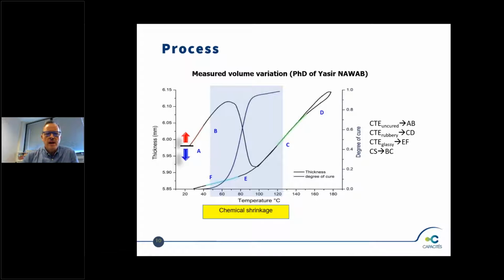And the other curve, which looks like a sigmoid from 40 degrees up to 120, is the y-axis on the right. This is the degree of cure. So we come from 0 degree of cure at point A to 100% degree of cure at point C. From A to B, the resin is liquid. You expand its volume because you heat it up. Then from B to C, you combine shrinkage and a variation in the thermal expansion coefficient of the material, because the coefficient of thermal expansion varies depending on the state of the material.